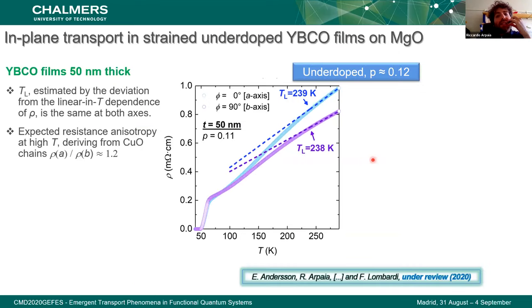And what we have seen is that on a thick film grown on MgO, if we study the resistivity versus temperature, we get something which is conventional. So the linear behavior at high temperature of the resistivity is the same on both the A and B axis directions. And the anisotropy that we have is about 1.2 between the two axes, which is expected considering the orthorhombicity of the cell and the presence of the copper oxide chains.